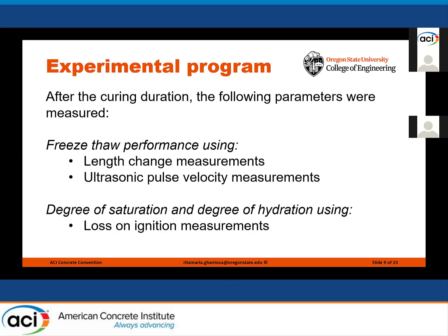And after the curing, for all the mixtures, we characterize the freeze-thaw performance using length change measurements and a conventional technique, which is the ultrasonic pulse velocity measurements. In addition, we measured the loss on ignition, and from this value, we calculated the degree of hydration and the degree of saturation. So in the next slide, I'll be presenting how we did the length change measurements and how we did the degree of saturation calculation.